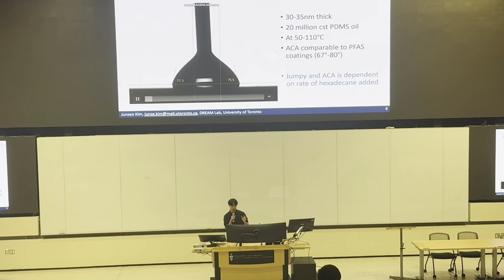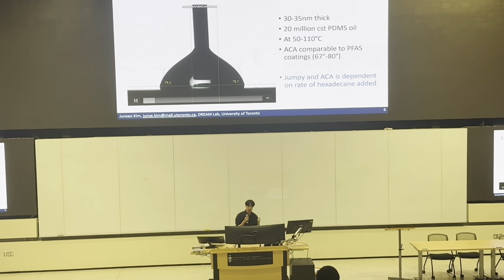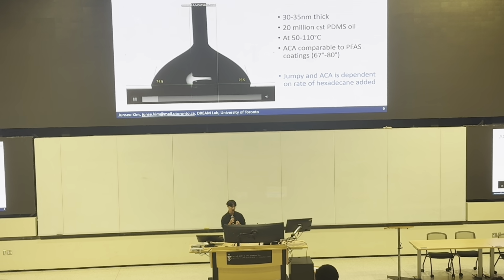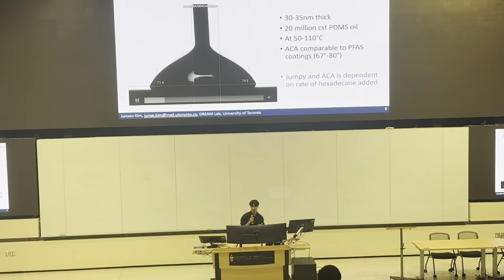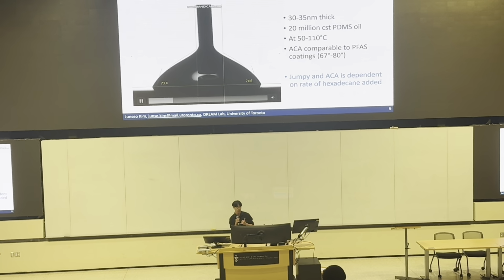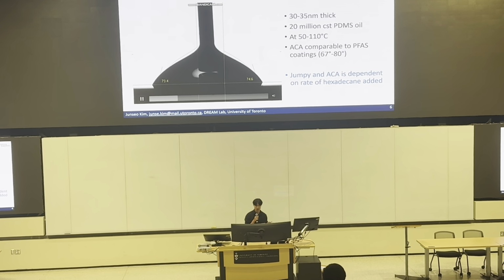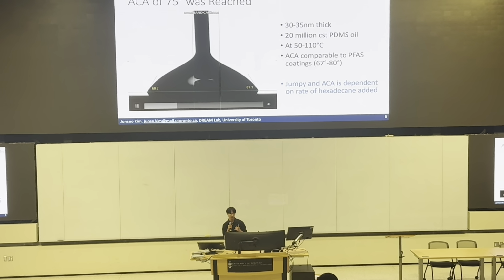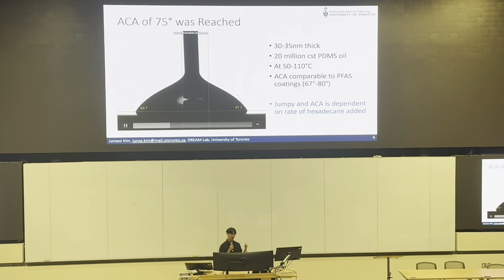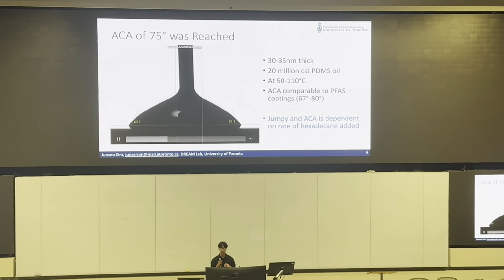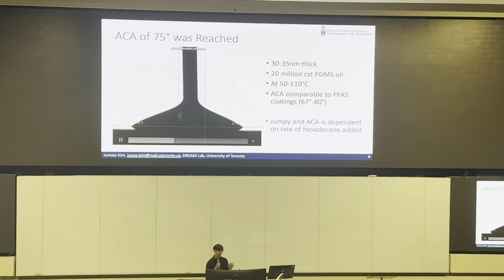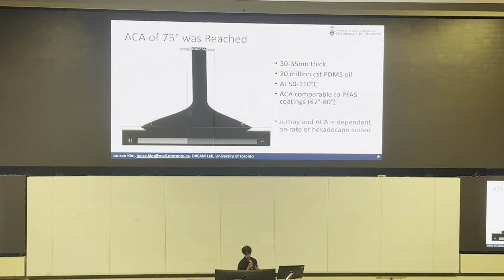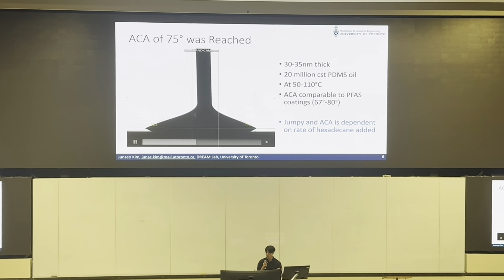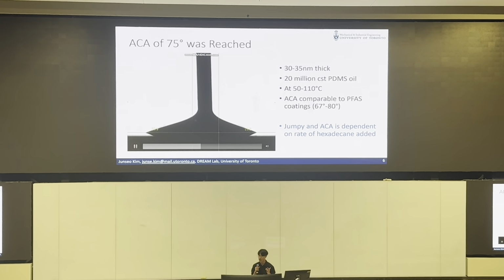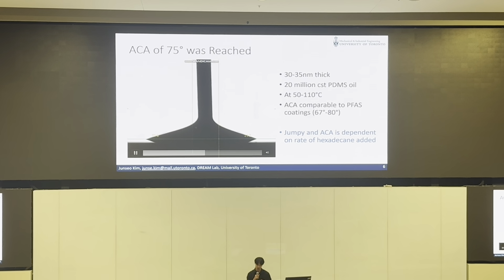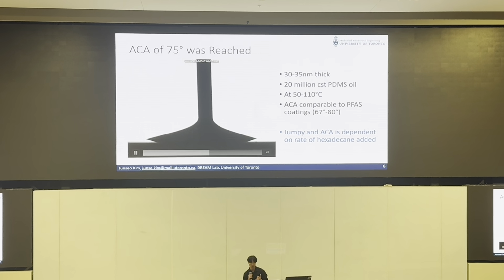So I created a coating around 30 to 35 nanometers thick. That's very big for a PDMS coating, using a 20 million centistokes PDMS oil. Centistokes is a measure of viscosity. The reason I'm using viscosity is because molecular weight is something that we want to increase, but that's hard to measure when it gets super high, but viscosity isn't. So I typically use viscosity to measure how heavy something is, like oil. And this was created at, like I said, 50 to 110 degrees.